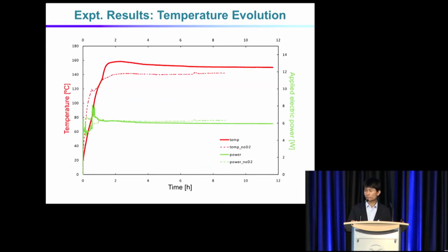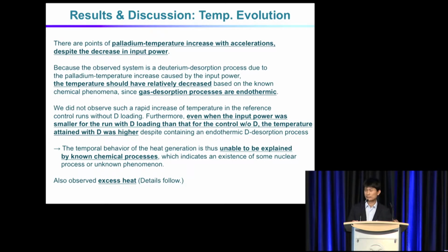First, I show you the temperature evolution result. We conducted experiments with and without deuterium loading, with almost the same amount of applied electrical power onto the sample. The solid curve is the case with deuterium, and the dotted line is without loading, so we see some difference in the temperature, although the applied electrical power is almost the same. Here we analyze what our results said.